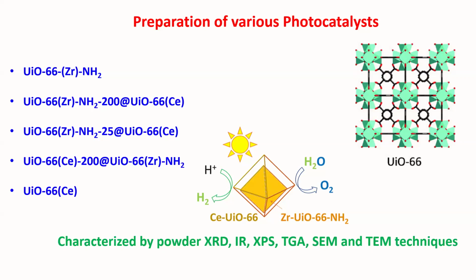And in this case, zirconium is going to be the core and UiO-66 cerium is going to be the shell, and the 200/25 is the amount: 200 milligrams and 25 milligrams. Again, in this case, UiO-66 zirconium is in the core and the other is the shell. And the fourth one we have changed: we put cerium in the core and zirconium as the shell. So typically we have two sets of MOFs, one occupying the core and the other occupying the shell. This is something like MOF on MOF, as people call it in the literature.